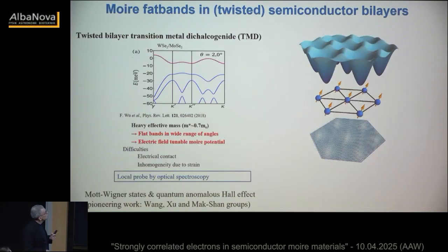Then came, in 2020, results on twisted transition metal dichalcogenides. Now we're dealing with semiconducting materials which have a reasonably high effective mass for electrons and holes. And in this case, you don't need a particular angle. All angles are good, and the angle can be used to change the periodicity. When you do your DFT calculations, you find that this system also exhibits nice and relatively flat bands. In these relatively flat bands, what you need to compare is the interaction energy at the lattice spacing to the bandwidth. And here in this example, the bandwidth is about 10 millielectron volts.